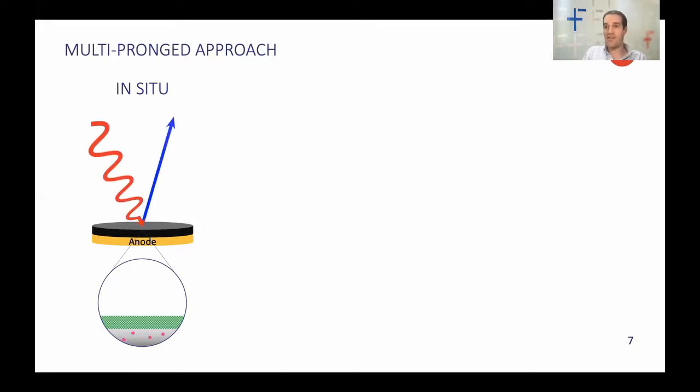And this is connected to the measurement system and can be done repeatedly, so we can look at the same electrode as it's cycled to different potentials, allowing us to remove many of the sample to sample variations you might be getting with ex situ methods. But it still doesn't allow us to look at intermediate species that might be forming.